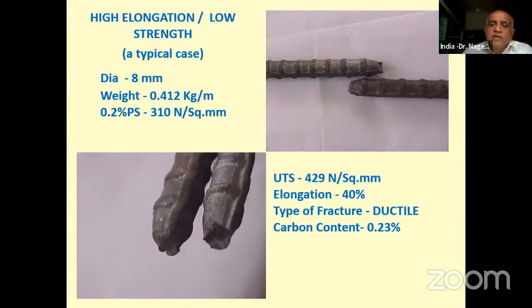UTS is again less, 429. Elongation is more because it's a highly ductile material. It is not having higher strength, but elongation is 40%. Type of failure is ductile and carbon content is less actually. It should have been 0.25. 0.25 is the minimum value, whereas it is 0.23 carbon content.